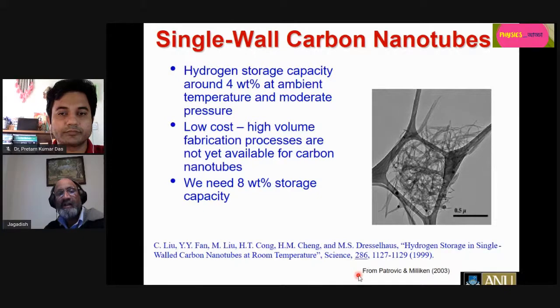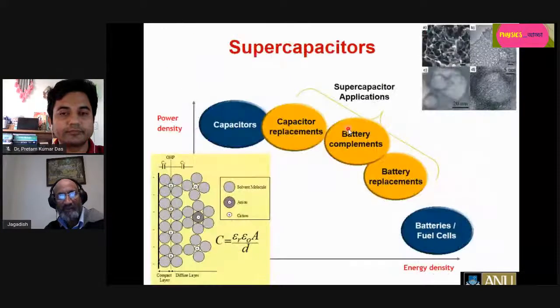She's from MIT. And she has shown that carbon nanotubes, which I've shown you earlier, because of the large gap in the carbon nanotubes, you can store hydrogen of about 4% at that time, about 20 years back. So now people are able to really enhance the storage capacity quite significantly. That means you don't use high pressure hydrogen, and you can release this hydrogen from these carbon nanotubes by heating it whenever you need it. Otherwise it's sitting very close to atmospheric pressure or so, which becomes much easier and much safer to deal with.